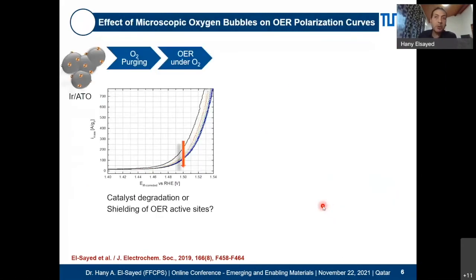In order to show this, we did a very simple experiment. We started linear sweep voltammetry, of course, in the oxygen region, evolving oxygen, using an iridium ATO catalyst. This is a homemade catalyst. We have a paper that we published before about this, and you can see that when you keep cycling, within only 20 cycles, the current decreases. Of course, this cannot really be catalyst degradation. I mean, this would be a really, really bad catalyst.